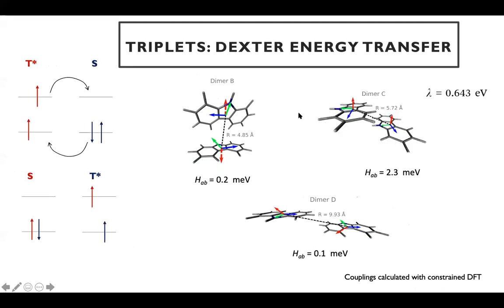So what other kinds of processes can we have? And I talked before about exciton couplings. If you look at the triplet states, for example, and try to find Frenkel excitons there, you will see that you don't get typical delocalized Frenkel excitons. Essentially, what you get is a very localized excitation on one of the molecules.